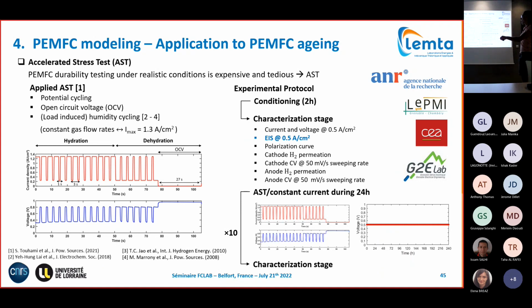We always switch between high current and low current, meaning low potential, high potential. We have a period with mostly high current operation, meaning a lot of water production, so we have good hydrated conditions. Then we have a period with mostly low current operation, meaning less water production, meaning dehydration periods. And then we finish with a sequence at OCV, supplying hydrogen and oxygen, which should induce chemical degradation of the membrane. One sequence lasts 105 seconds, and at the end of the sequence, we start again and cycle again. This is automatically done for 10 days. We have a really accelerated aging.